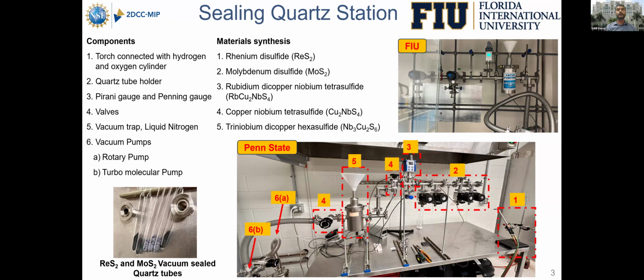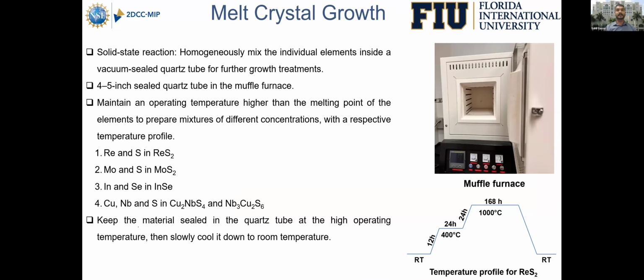hexasulfide. Moving forward to our first crystal growth, which I have learned, the melt crystal growth. It's more like a solid state reaction where we want to homogeneously mix the individual elements inside a vacuum sealed quartz tube for further growth treatments like CVT and flux. Usually we made a 4 to 5 inch quartz tube and put it in the muffle furnace, maintaining an operating temperature higher than the melting point of the elements.